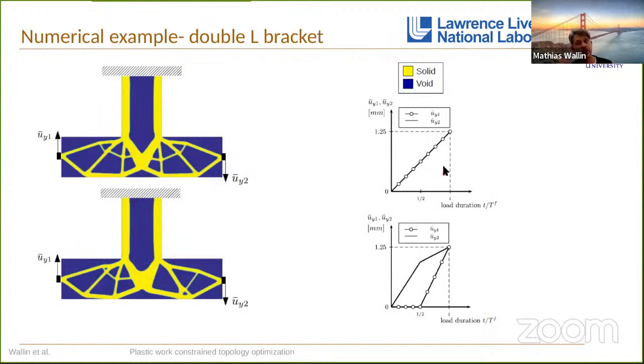Another advantage of including plasticity is that now you can actually handle path dependence. In this case, just to illustrate, it's kind of a torque. You displace U on this side and this side, and you do that simultaneously in this way. You will see that you get a fairly symmetric design. But if in this case you take U1, you clamp this one for a while, and then pull this one, and then delay the motion of this point slightly, and then when you are halfway, you increase both so that you end up in exactly the same end state.